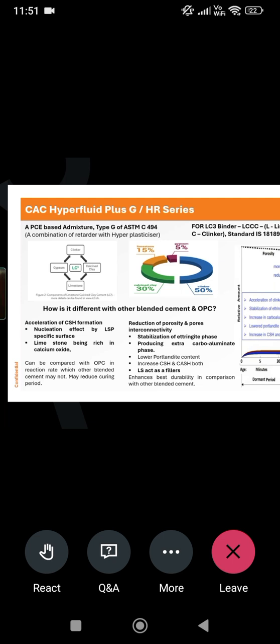But here limestone is acting as an SCM, supplementary cementitious material. Why? Because it is also producing some compound, called carboaluminate, which is not happening in any blended cement or OPC. This is the main difference, right? So it is also a ternary. And how is it different from other blended cement and OPC? They are only producing CSH, and here they are also producing monocarboaluminate and hemicarboaluminate, along with CSH, CASH, calcium aluminosilicate hydrate, calcium silicate hydrate. And the most important thing is it is stabilizing the ettringite. This is the main funda of this cement, and no other cement is able to stabilize the ettringite.